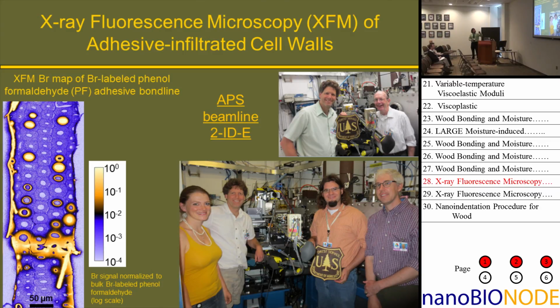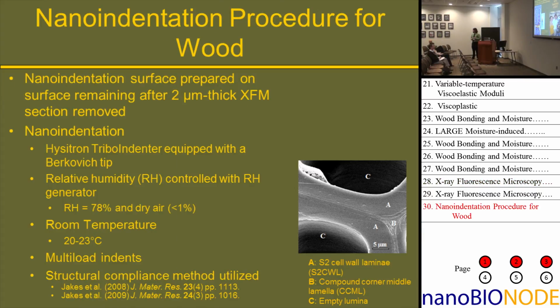And then what we do is, we cut this 2-micron section. That means you had the wood block underneath, and I can go to that wood block and do the nanoindentation on the exact same wood cell walls that I took this section from. So it's the basic procedure I used. The surface was prepared exactly from where that 2-micron thick section was.